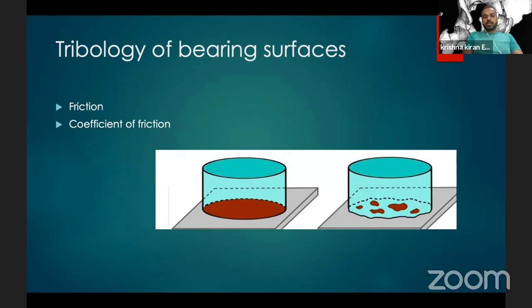So it is sufficient to say here that if you have the picture on the left side, you have two surfaces in contact with each other, and what you assume is that the entire surface is in contact. But what actually happens in reality is there are micro asperities on each surface, and the actual contact area is equivalent to the highest asperities on either of the surfaces. We all know that as the surface area increases, the contact stresses will come down. But in a real life scenario, the actual contact area is very small because of surface roughness and micro asperities on the opposing surfaces.